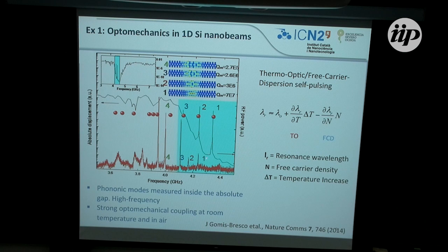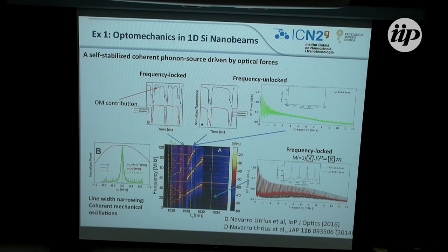Many of these interactions are affected by what is called the thermo-optic and free carrier dispersion effects. It is a combination of these two effects that shifts the resonances of our interacting phonon cavities, and then these particular terms here, one depending on temperature and the other on carrier concentration, will provide two competing mechanisms. And these mechanisms will result in the system pulsing at the particular frequency that is being selected. Pulsing means that you have like an oscillator. And in the case here, when the frequencies are locked, you have a particular shape of the pulse that you are detecting. You have a significant change when they are unlocked. And what is very interesting is that you see, like in lasers, a line narrowing for the coherent mechanical oscillations.